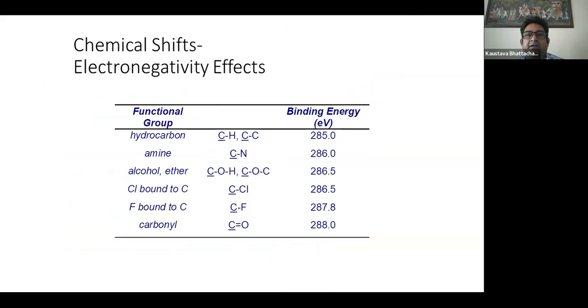So for example, if we check for a hydrocarbon, like CH or CC, we usually get a binding energy of say 285.0 eV. Whereas if we check for an alcohol or an ether, we get almost a 1.5 eV shift. If it is bound to fluorine, we get a stronger shift, like almost 2.8 eV or almost 3 eV. Or if it is bound to a double-bonded carbonyl group, a double-bonded nitrogen group or a triple-bonded nitrogen group, we have a different shift. So accordingly, we can say how the carbon is bound to a particular group, and also find qualitatively the population, how much of that particular group is present.